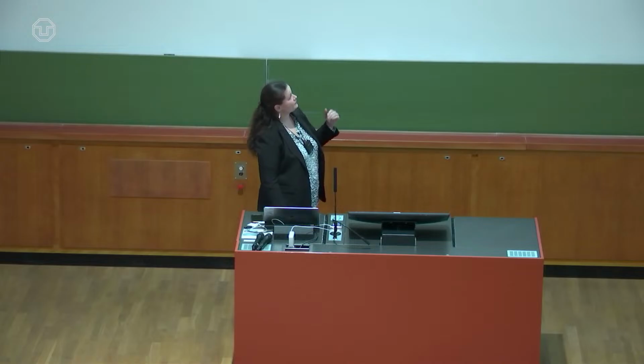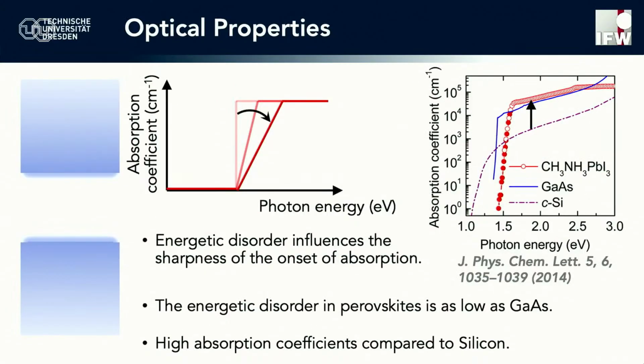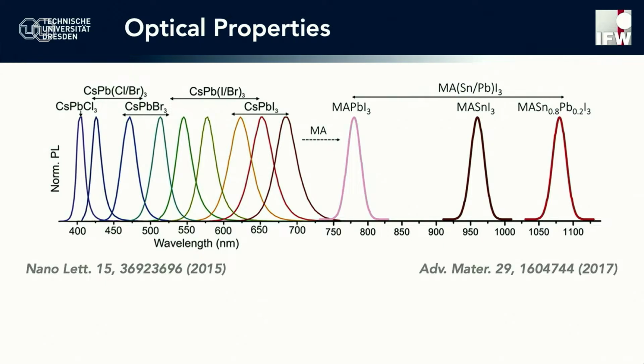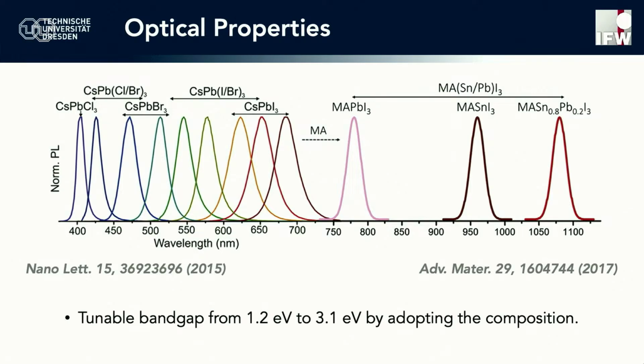Now, we see here an example for a perovskite, but of course you saw we can have many different combinations of elements that we could put together. While in the case of silicon or even gallium arsenide, we have one band gap, one material, here we can tune the band gap. We can simply change the composition, for example, ranging from cesium lead chloride all the way in the blue range with very large band gap, and then gradually changing the halide to bromide and then to iodine across the visible range, and then finally going to mixed tin lead systems, which go all the way into the near IR. And that means that with a single material, purely by changing its composition, we are able to tune the band gap from 1.2 electron volt to 3.1 electron volt.